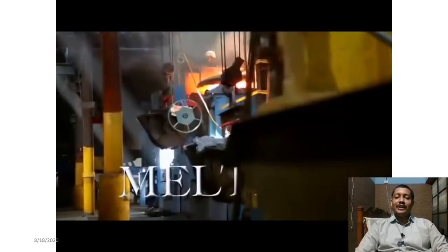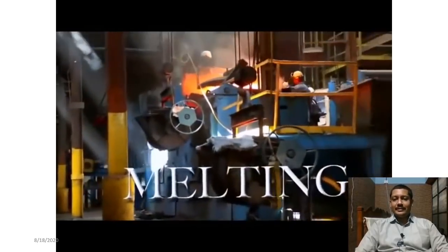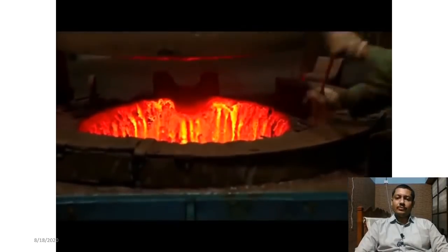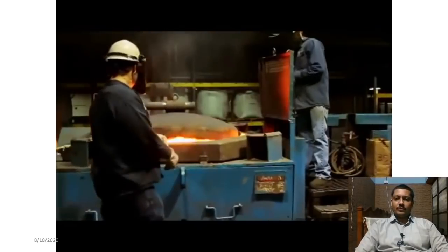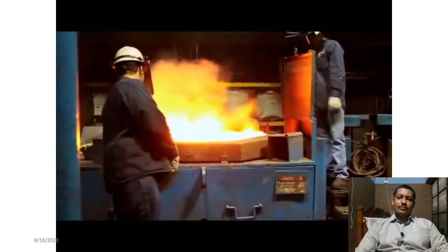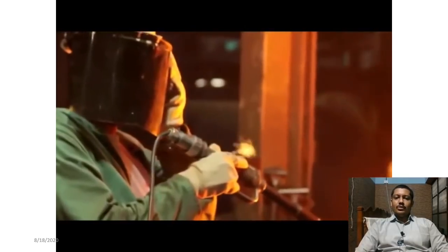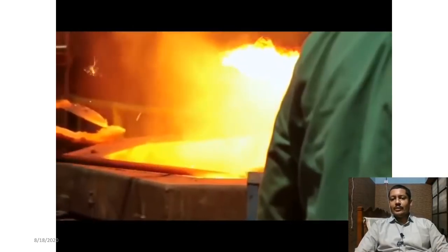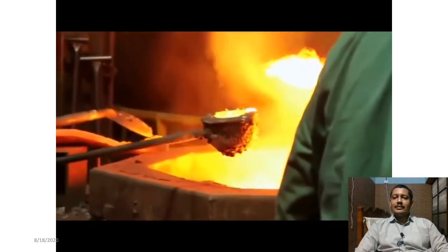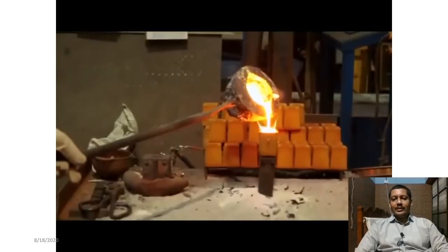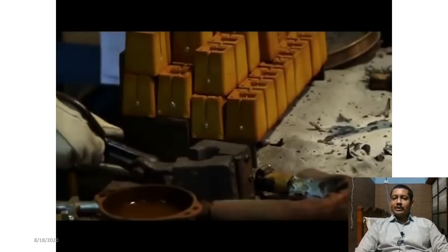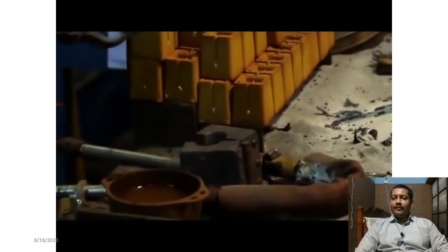This is an electric induction melting furnace. The furnace runs at 2,800 degrees Fahrenheit and can hold up to 4 tons of molten metal. It takes 15 minutes to melt all the 2,000-pound charge into a super hot liquid metal. Temperature and time you have to set over there. It's at this point we take a sample. After a certain time, depending on the spectrometer results of this sample, workers will add measured amounts of alloys to the iron bath. So spectroscopic analysis will be performed.